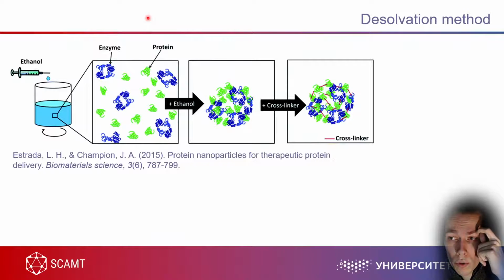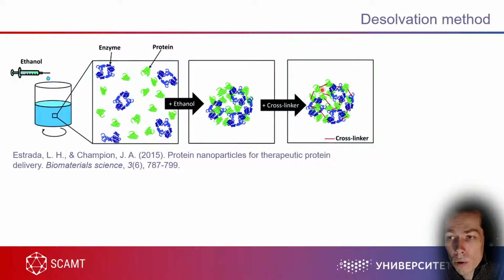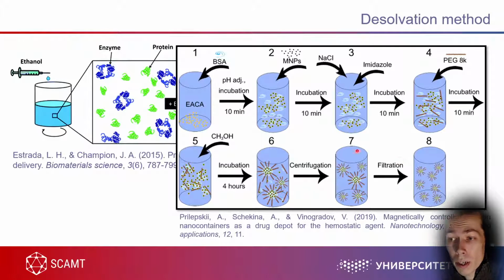If you do not want to use cross-linkers, because cross-linkers are very toxic, basically some kind of glutaraldehyde or something like this, you can use a method that we discovered previous year, without using any cross-linking agents. Just add some PEG, polyethylene glycol, in your media, and this PEG will cover these particles. So no cross-linking, just a PEG shell around these particles. And this PEG shell will stabilize these particles, so they will decompose over maybe 2 days, providing a slow release.